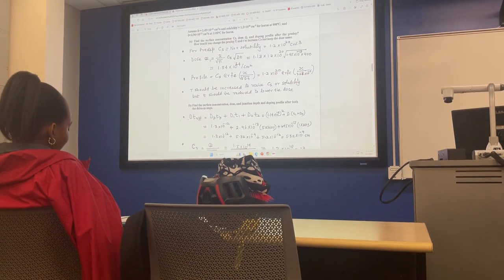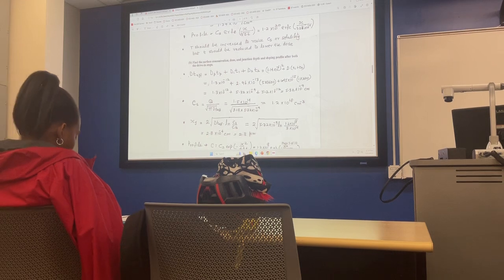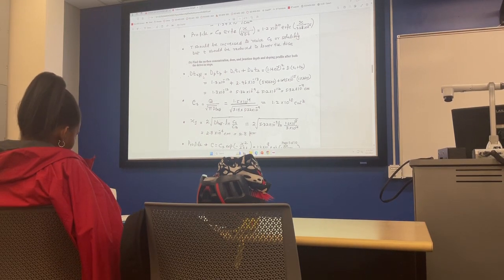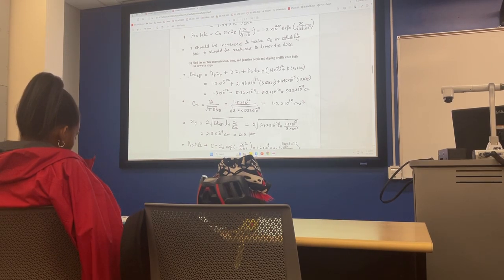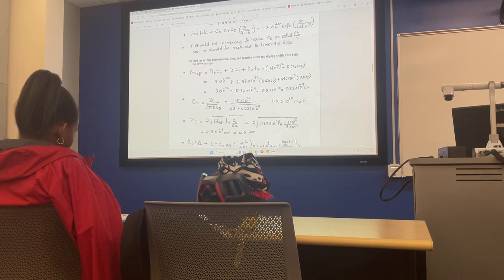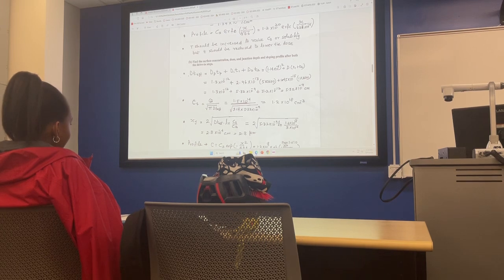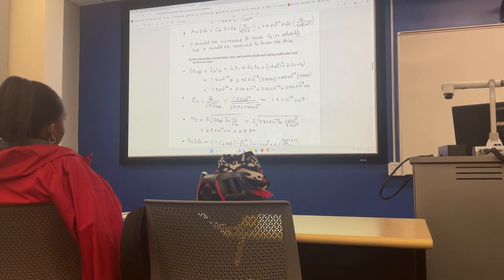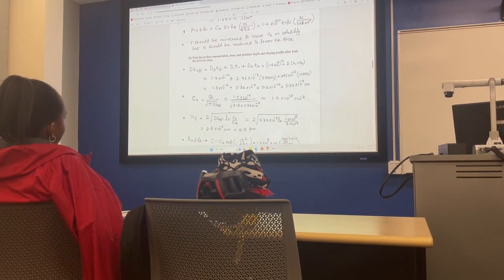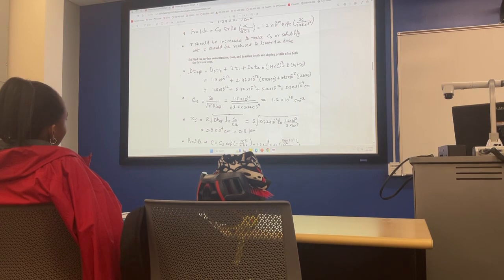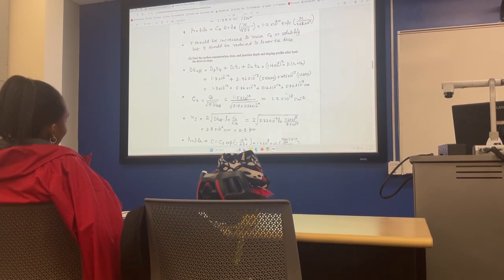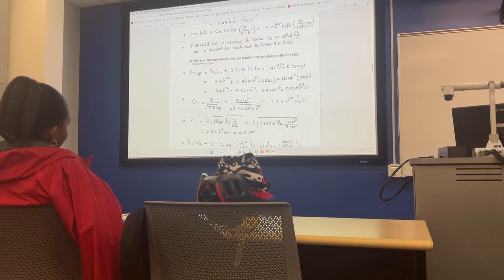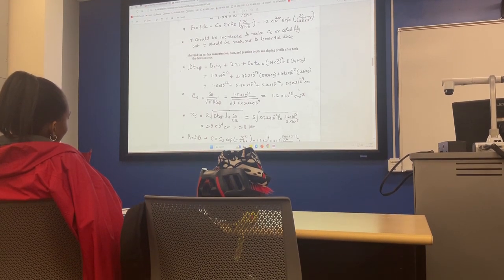Okay, next question is after driving. So this was about the pre-dep. I said, okay, give me all the information after you drive, and I've got 2 drive-ins. So you said, no big deal. All I have to do is get my Dt effective. That's all there is. So you said Dt pre-dep, Dt first drive-in, Dt second drive-in, and D and t are given to you. So you just put those numbers here, and you find that this one dominates. So the first thing to do is to get the Dt effective, which is 5.3 times 10 to the minus 9. So once I have Dt effective, the whole game is over.